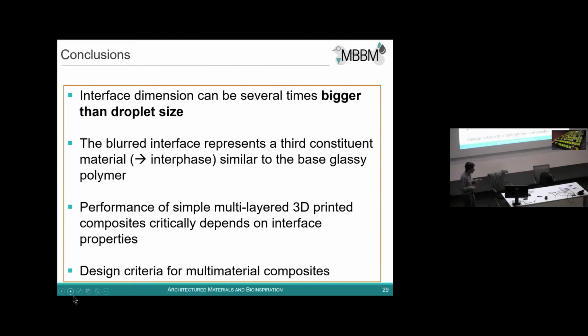So in conclusion, here we have proof that there is a formation of an interface in this 3D printing multimaterial approach, which can be several times bigger than the droplet size. And then this blurred interface is actually an interphase. So it's a third material, which has properties which are more similar to the glassy polymer, both storage properties and dissipation properties.